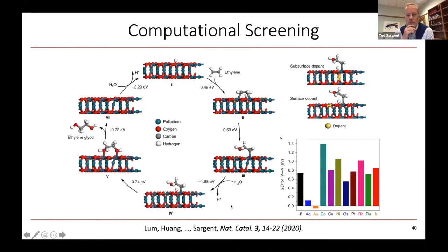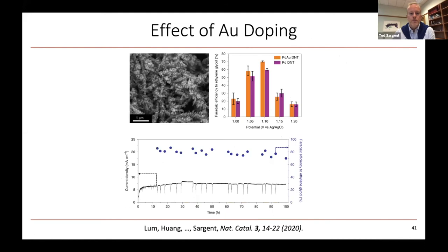which is one of the catalysts in which it had been previously proven, between step four and step five shown in this reaction was the largest energetic barrier. So they focused on, again, a doping strategy, a kind of nanomaterials doping strategy, where they screened possible dopants like silver and gold and cobalt and copper into the palladium. And they found that they were able to reduce this rate limiting step from theory if they could dope in gold.